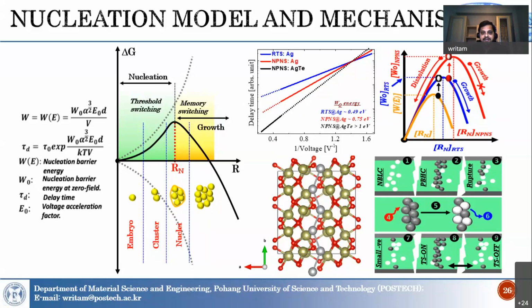After theoretical calculations, we have seen that the barrier height for silver devices compared to silver tellurium devices, with and without the NPN scheme, shows that with the vacancies it can increase the barrier height, and the same holds true for silver tellurium devices. The main origin of this behavior comes from the difficult nucleation in those devices.